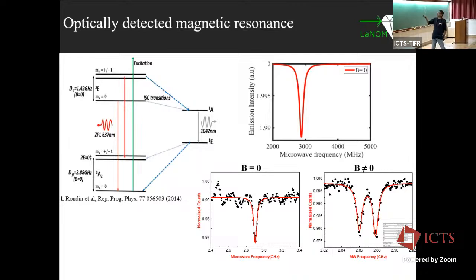This is something we simulated by solving the Hamiltonian of the system. But a few weeks back, we successfully measured it. This is with the magnetic field at 0. We get a nice ODMR dip at 2.87 gigahertz, but the contrast is very low, only 5%.